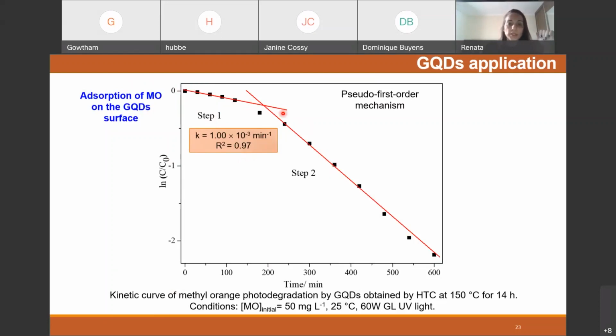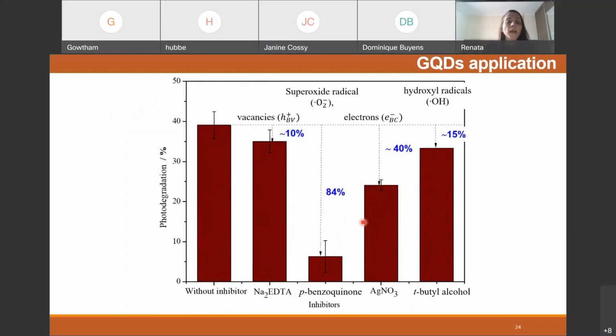The second stage was attributed to photodegradation, and this is the kinetic constant, and the adjustment was very satisfactory, with a coefficient of determination closer to 1.